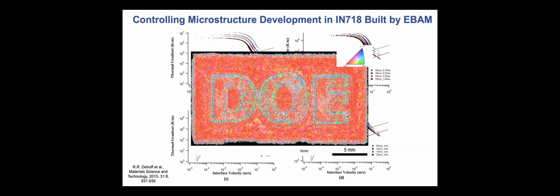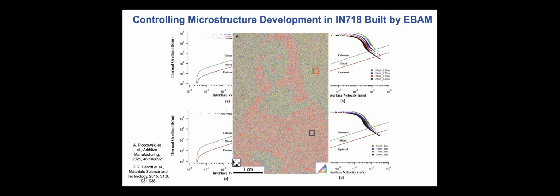And this is a nice example of post-mortem characterization, where this is crystallographic mapping. Simply by turning on and off the columnar to equiax transition during processing, they're able to spell out in the grain structure of the material DOE into the microstructure, which is pretty cool and a nice example of microstructural control with additive manufacturing. A more updated plot on that is this one here, which is putting the Mona Lisa in the microstructure, so sort of paint by processing.